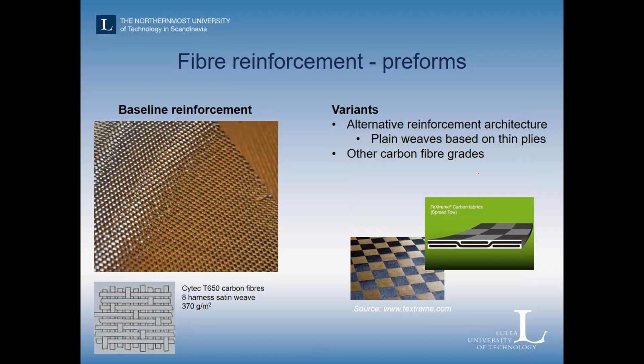The processing of the high temperature material is done at high temperature, meaning that we need to adapt the reinforcement to that. So we can't really use non-crimp fabrics with stitches; we use primarily weaves, carbon fiber weaves, and the baseline material we've been using is an 8-harness satin weave most of the time for the development work, but also in some cases other alternative architectures, like plain weaves, and thin ply materials, which are lower surface weight reinforcement that can produce really thin ply composites. These are a bit coarser when it comes to the structure.